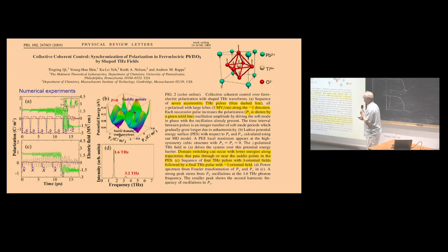And here is a first theoretical paper about the possibility to switch polarization in ferroelectric lead titanate. It is from the group of Rappe, and I will make some experiment here. I have an oscillator. It is vibration of atoms in this lattice, let's say vibration of titanium in the middle of this oxygen cage, which is responsible for the displacement, for the appearance of ferroelectricity. And what they propose is that we have vibration with some amplitude, and if you pump it in phase, you can enhance the amplitude, and they assume that you can come from one minimum of polarization to another one.